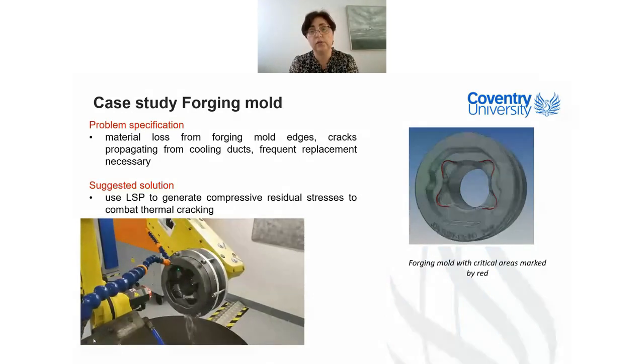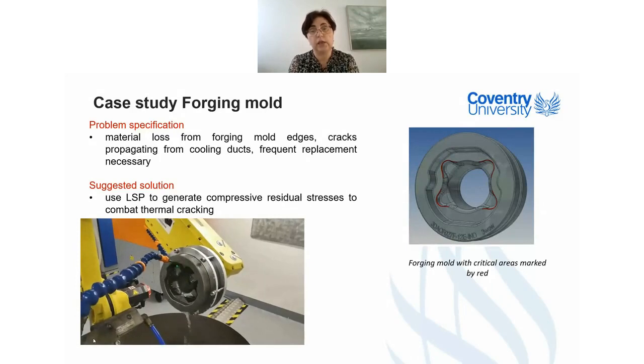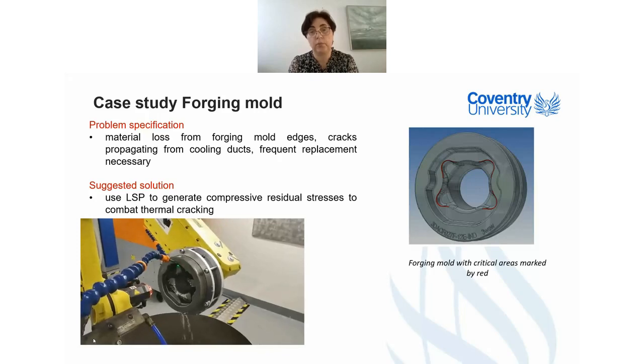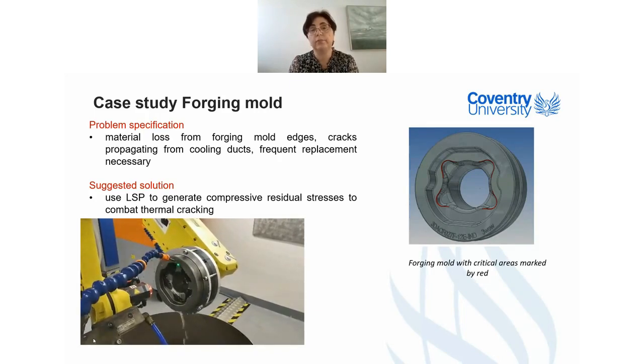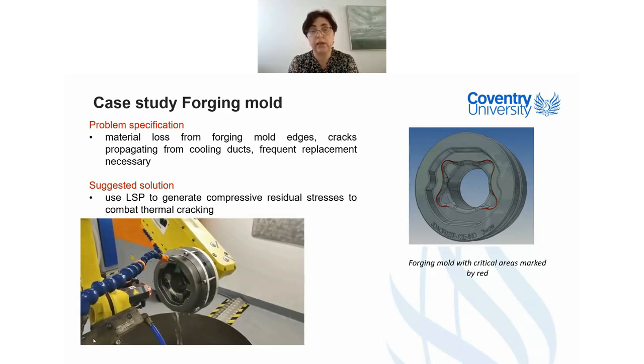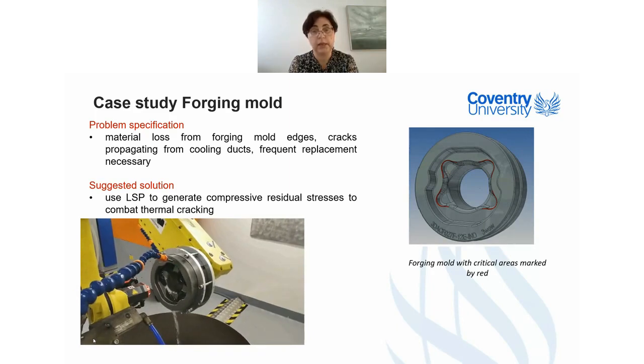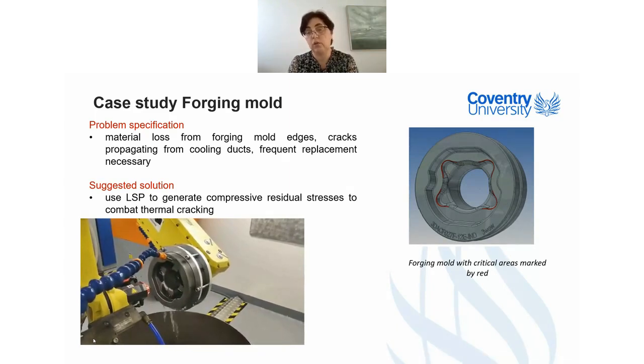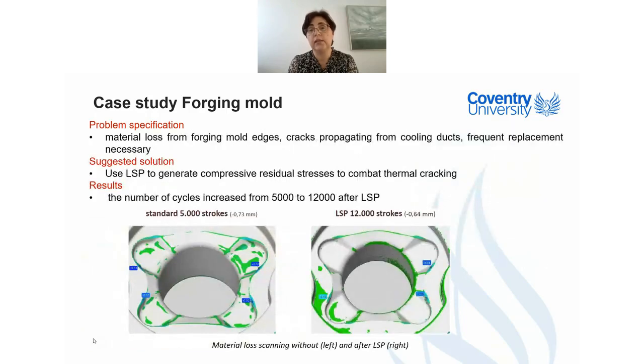This is the tooling industry. And here what I would like to mention is that it's very important that you understand the problem which you are treating. In this particular case, there are two problems. One is related to cracking, such as fatigue or thermal cracking, and another one is related to wear. Thermal cracking we were able to solve with laser shock peening, but the wear problem, which is usually solved by increasing the hardness, we were only slightly influencing, because laser shock peening is not a method which increases the hardness. So the problem in this particular tool was solved by first doing laser shock peening and then applying very hard coatings.